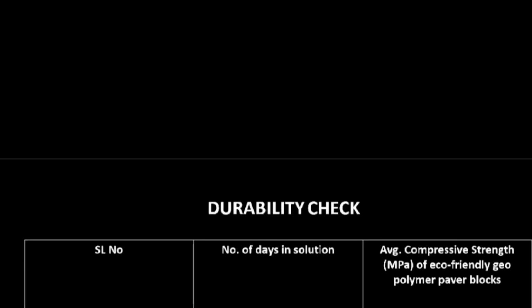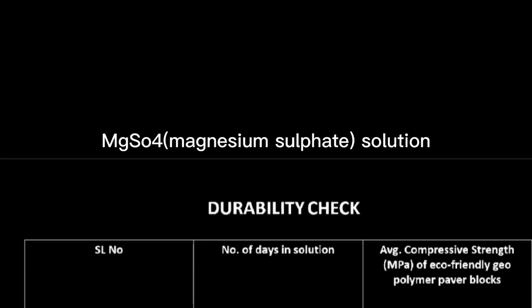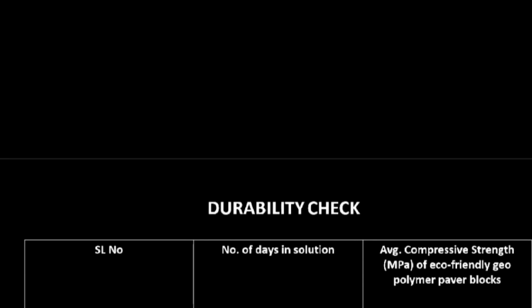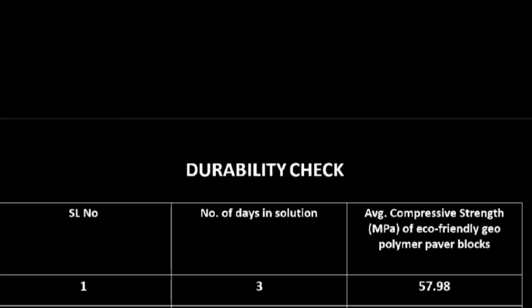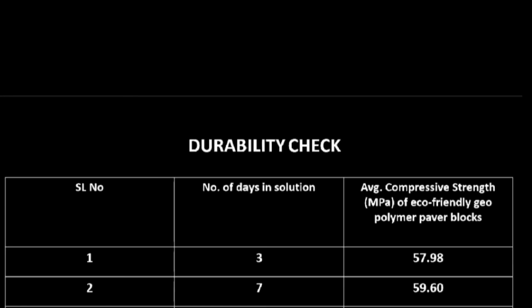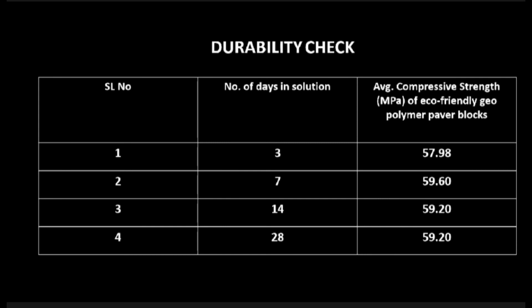A durability check was conducted, placing the GPC product immersed in a 5% MgSO4 magnesium sulfate solution. And the following results were obtained. For 3 days of immersion, the strength obtained was 57.98 megapascals, at 7 days it was 59.6 megapascals, and at 14 days and 28 days it was 59.2 megapascals.